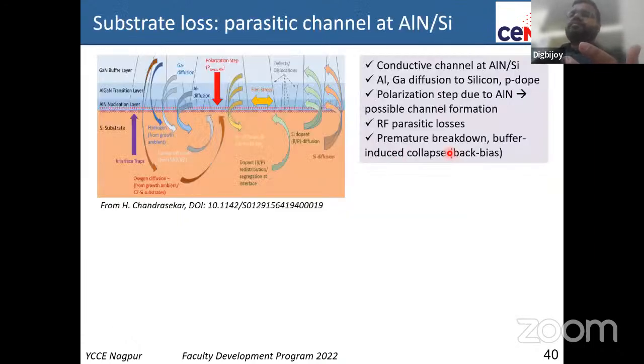This image is taken from Dr. Hari Chandrasekhar's paper that was published a few years back on the different mechanisms that lead to loss. For instance, nitrogen might diffuse. There may be hydrogen from the growth. There may be oxygen diffusion. All this might lead to RF or microwave loss, dislocations, stresses. So many factors can lead to RF loss.